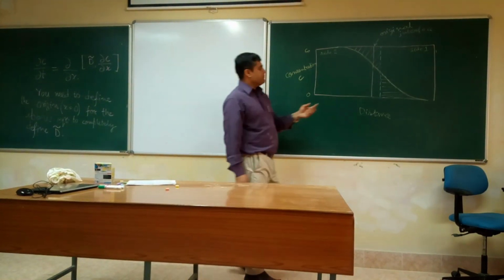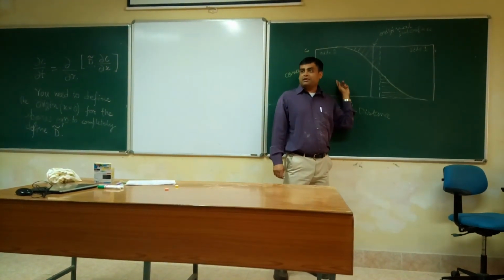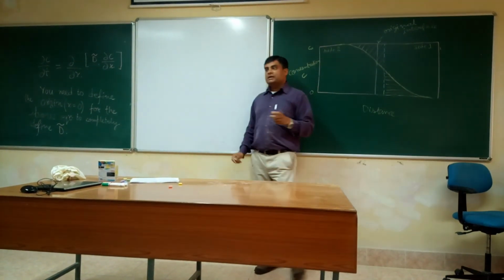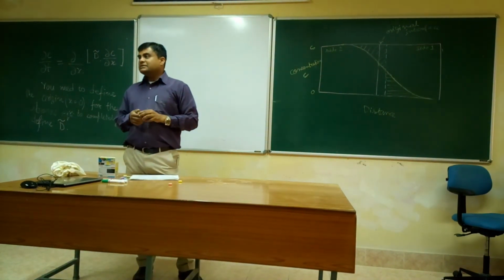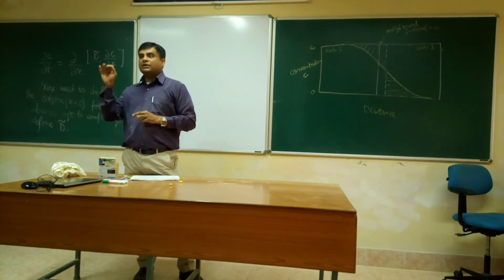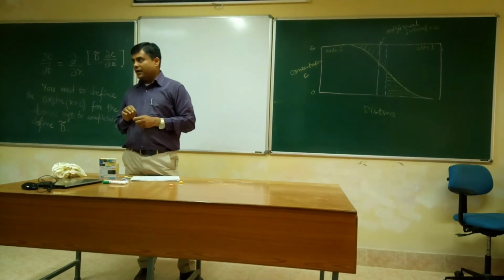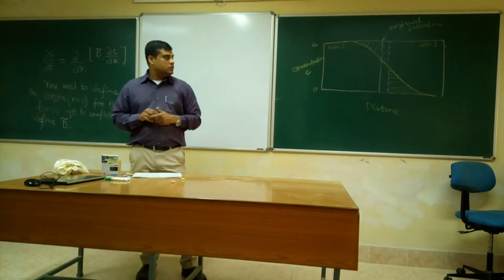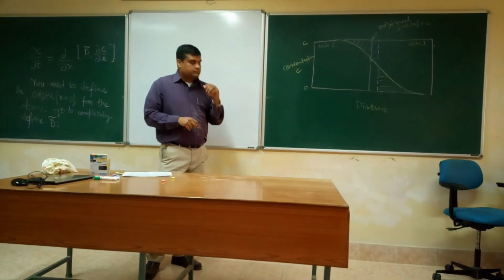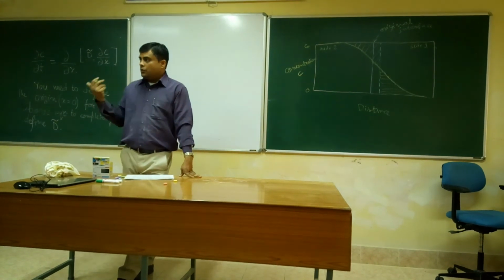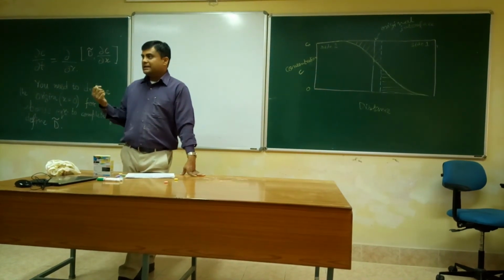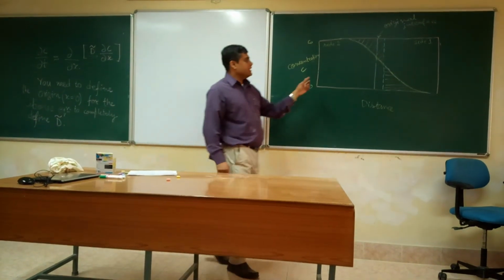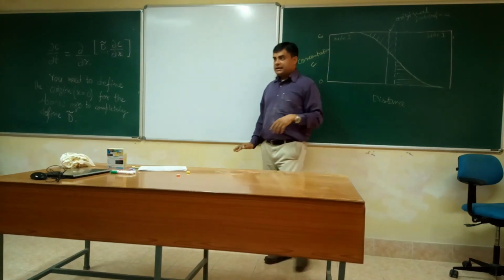One atom is coming from this side to that side, another atom going from that side to this side. The element of lower melting point, on the side rich in it, will diffuse faster and go to the other side at a faster rate compared to the other element going in the opposite direction.